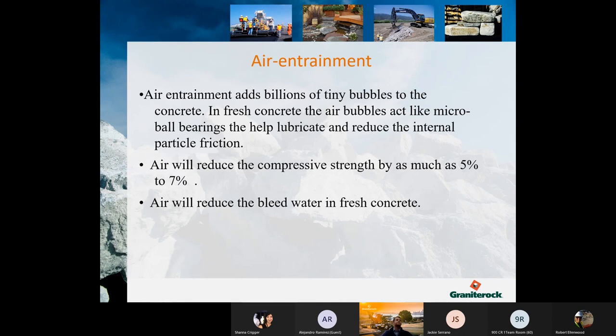So starting with air entrainment. Air entrainment adds billions of tiny bubbles to the concrete. In fresh concrete, air bubbles act like micro ball bearings to help lubricate and reduce the internal particle friction. Air will reduce compressive strength by as much as 5 to 7%, and it also reduces bleed water. Besides a little bit of finishability for using it, air entrainment is usually mostly used in freeze-thaw environments. We're lucky enough to not have too much of that around here. I think more of Sierras or places that have cycles of freezing and thawing the same day.